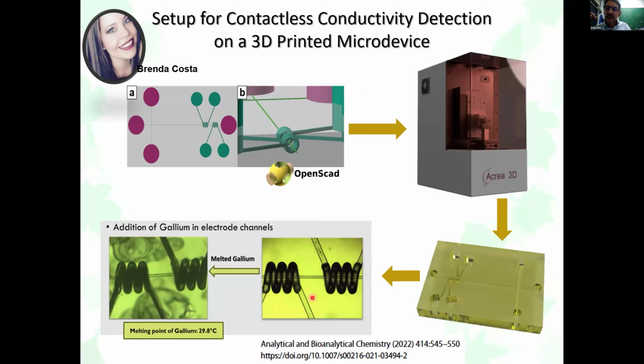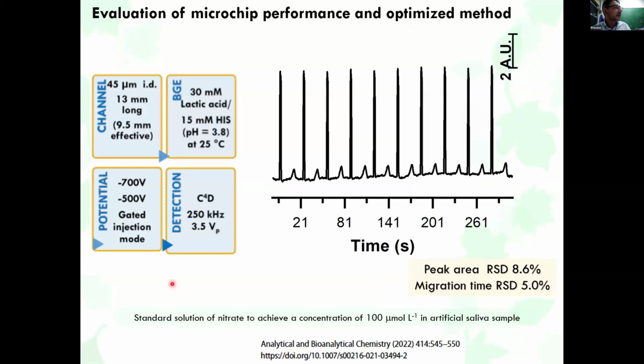So the idea is to use this circular spiral device as electrodes. After the device was printed, we injected gallium. Gallium has a low temperature of fusion, around 30 degrees Celsius. So we inject gallium here and get electrodes for contactless conductivity detection. So here's a separation of nitrate using this device.